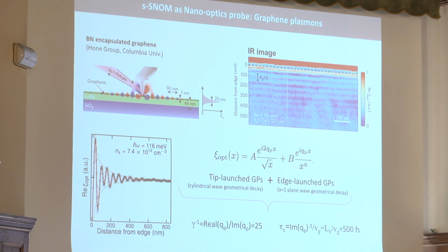So for propagating applications, this is interesting. This is a good figure of merit, dimensionless. For other properties, I like this more in our works because, for me, it's more intuitive for cavities and so on: the lifetime. So how much time is the wave traveling? You can do this by dividing the propagation length, extracted from this decay, by the group velocity.